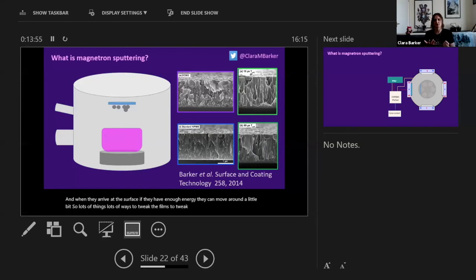And I've put on screen some cross-section micrographs. The different parameters don't really matter, but one of the images looks a bit like cornflakes piled on top of each other with lots of gaps and spaces between each other. And some of the other ones look a lot harder and denser, a bit glassier. And so this is the same material, similar properties, but just changing the energy or the background pressure that we're giving to it. Of course, by eye, you can't see any difference because the cross-section of these micrographs is about 1.5 micrometers.